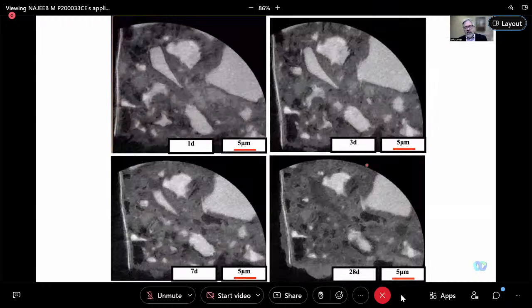In fact, this was maybe one of the more useful kinds of results, because the image, remember, is three-dimensional, but these are two-dimensional slices that are aligned and matched with each other over time. We have 1 day, 3 days, 7 days, 28 days, all shown together. Up in the top left, we have a particle. Now look how it has changed by the time you get to 28 days. It's gone. That light area, a high density particle, is now a low density void, because it's dissolved and hydrated and been part of the hydration process.